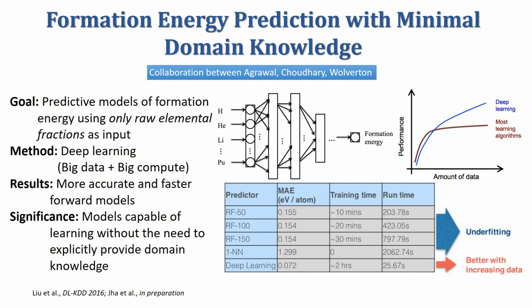by itself. And then it also figured out, for example, we gave it NaCl and MgCl, and it could figure out that all charge balanced compositions were clustered together, and not charge balanced were somewhere else when we looked at the activation graphs. So it was very exciting that this model can actually learn chemistry for the first time, where we can be confident that this can be good prediction. We also made other tests.